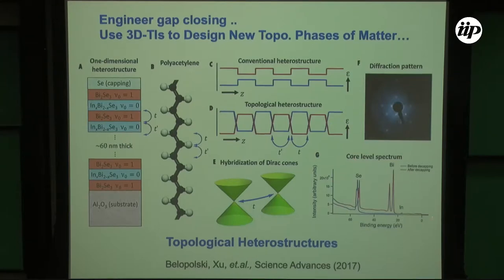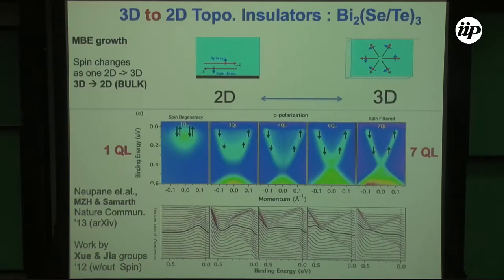So we can do core level spectroscopy and look at the ratio of selenium to bismuth. If you're looking at this layer, then there should not be any bismuth. So if you decap enough, then you recover the right ratio. And also, if indium is on the surface, you'll see that in the spectra. So just to convince you that we have an internal diagnostic to figure out what surface we're looking at. Now, going back to your question.